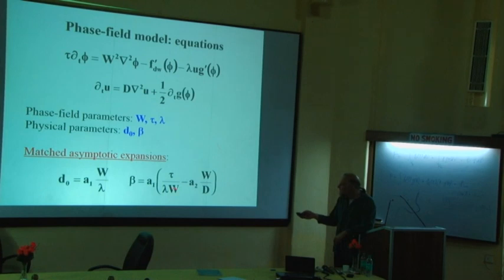The real difficult part is this one, for the kinetic coefficient or for the interface mobility, because you see that this expression has two terms. Okay? Now, where do these two terms come from? You can exactly understand their physical origin. The first one here, this is exactly the same that we got for the magnetic model. That is, this is the drag force that you get when you put a homogeneous driving force. Okay? So if you put a homogeneous magnetic field, that's what you get.